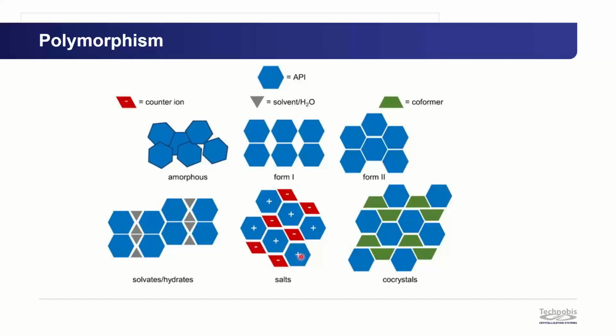And then when a secondary molecule is incorporated but is not a liquid, it can form either a salt or co-crystal. And this is defined by whether there is an exchange of the bonding proton. If there is, we get ionic bonds forming, and this forms a salt. And if there is a shared proton between the two different molecules, that results in a co-crystal.